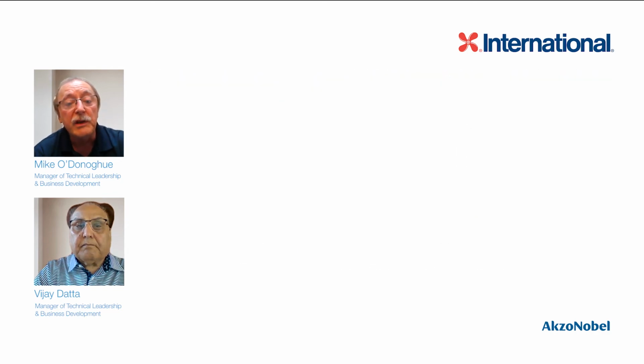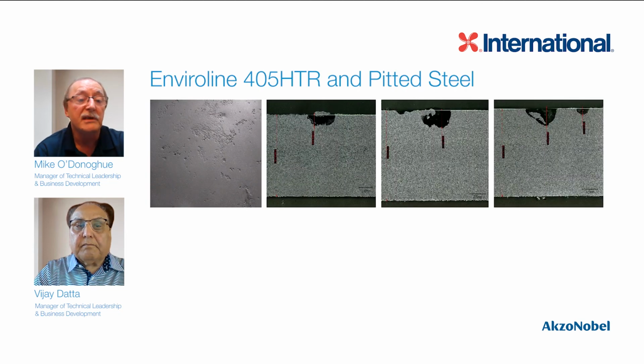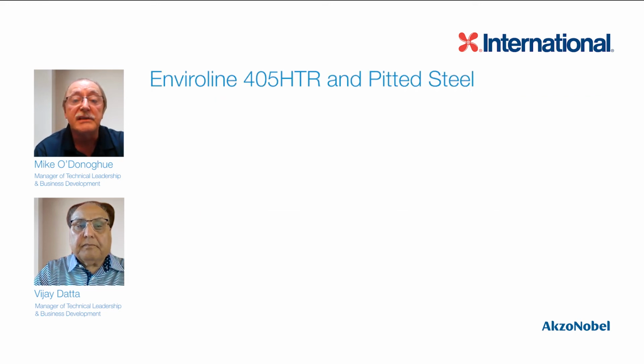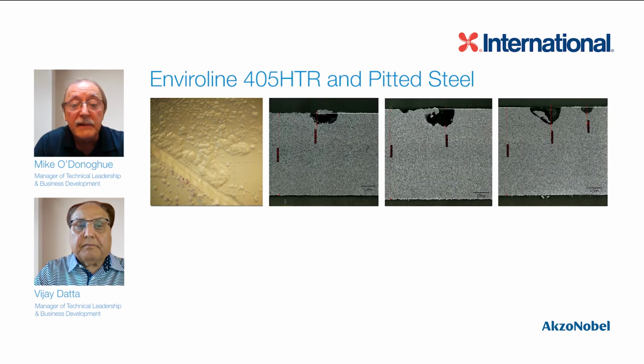But in real life, of course, when you're inside of an above ground storage tank, oftentimes you don't have a nice blast profile like that. You've got a surface to begin with, which is pitted, oftentimes with omega pits that we have to make sure we get inside and deal with. You'll come to that, I know, VJ. So that's one of the challenges there with that pitted steel. And in this next quick slide, you'll see that the coating, when it's applied on the surface, looks rather like the moon, as with covering the craters, as it were.